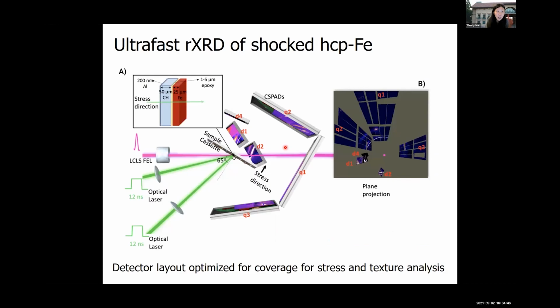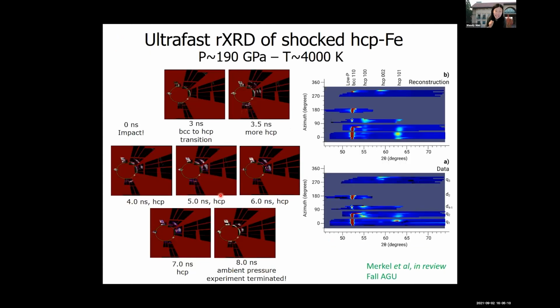You can also do ultra-fast radial X-ray diffraction. So we've heard talks about radial diffraction at a diamond anvil cell. We can also use a similar geometry where we have our pump laser close to 90 degrees to our probe X-rays, and then see how the texture development and lattice strains change with azimuth angle. And so this is a study that was led by Sebastian Merkel. I'm not going to have time to talk about it, but if you're interested, Sebastian's going to present something at AGU, but it's another capability that you can do using XFEL.